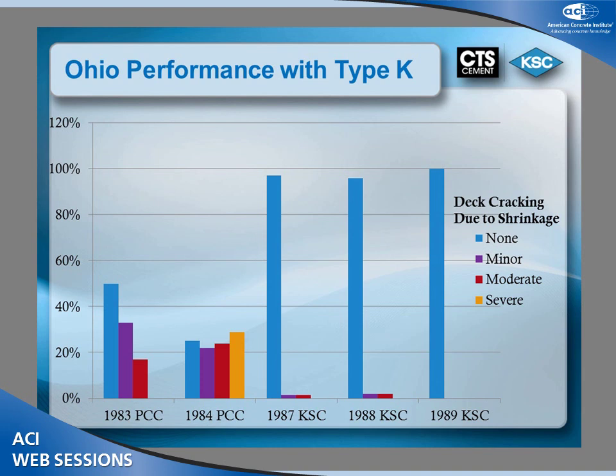When they went to the shrinkage compensating concrete, 87, 88, 89 time period, you can see that there is no cracking in over 95%. In fact, in 1989, the bridge decks there, 100% of them had no cracking.